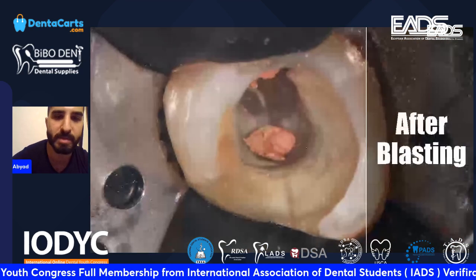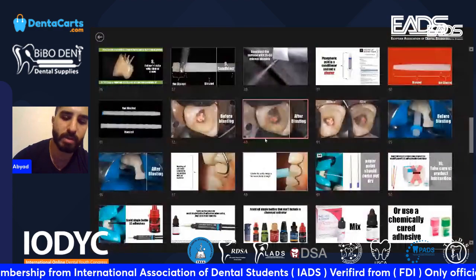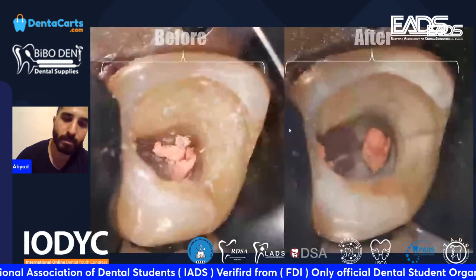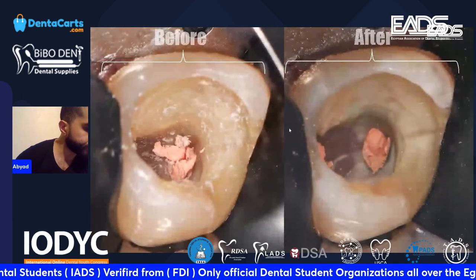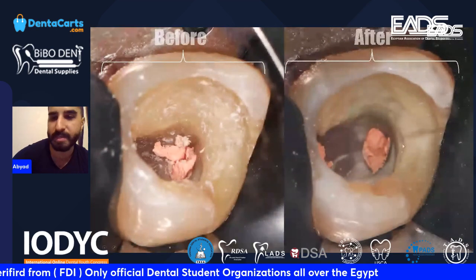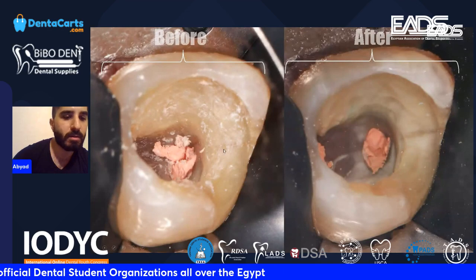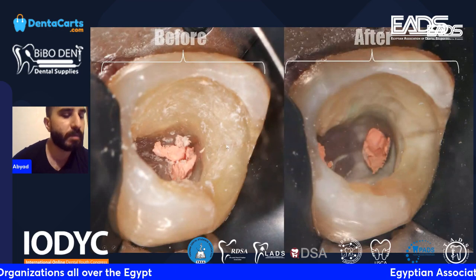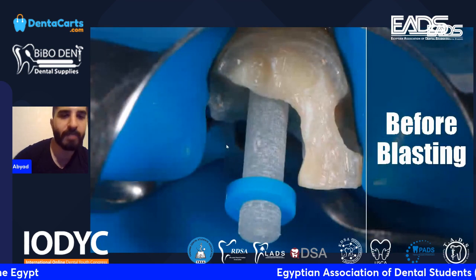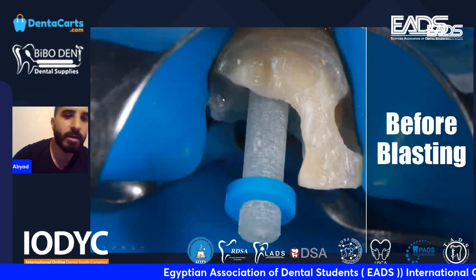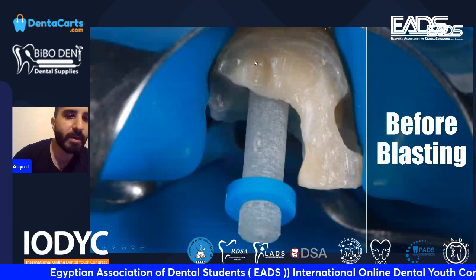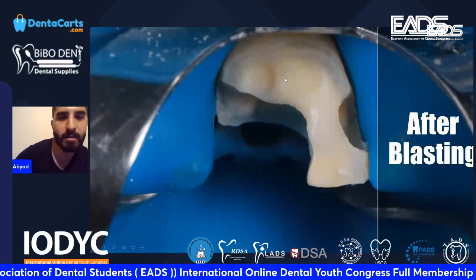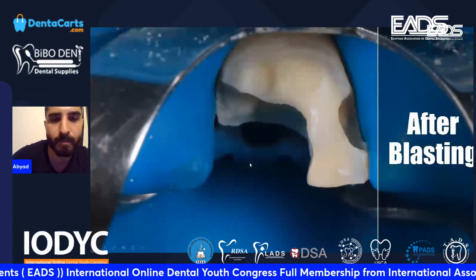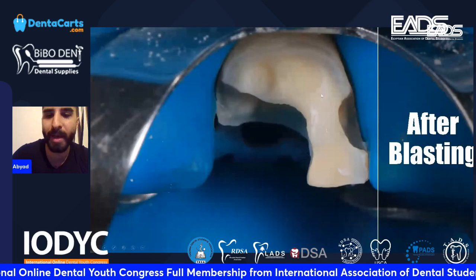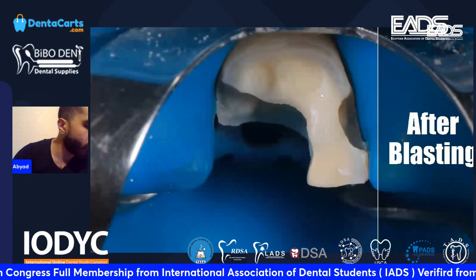You can see a crack in this area, okay? Before blasting, because of the presence of debris, it was not apparent. I couldn't see it, okay? Have a look at this crack in this area and how it was not visible because of the presence of the debris. Have a look at this tooth again. Debris, remnants of gutta-percha everywhere, and then I blast it and have a look. Beautiful, smooth, micro-etched surface that's ready for bonding.